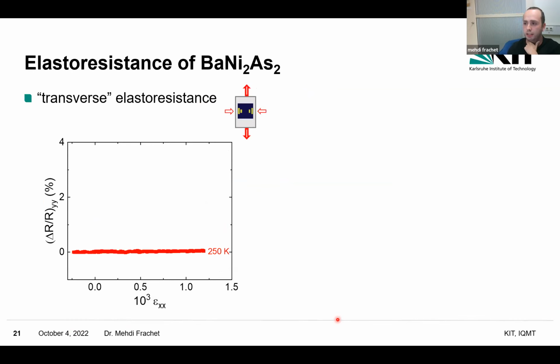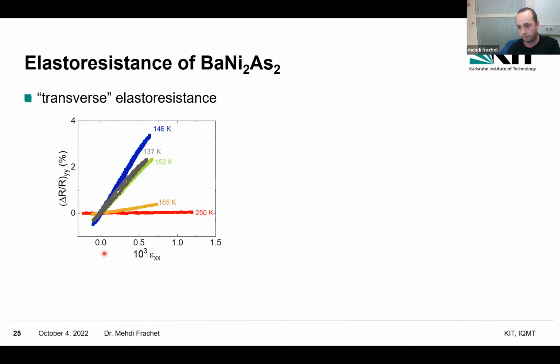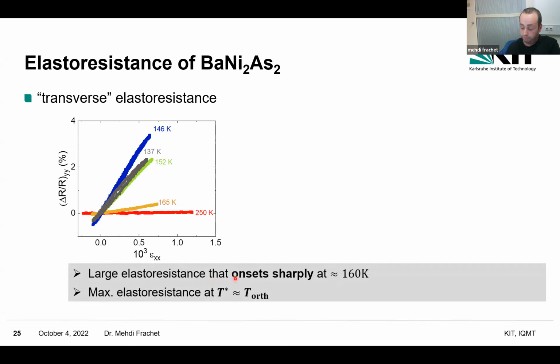Okay, now let's apply some voltage and have a look at the data that we got. That's transverse elastoresistance, so the electrical resistance is measured perpendicular to the pulling direction. Resistance as a function of strain, and you see that at high temperature there is not so much response to strain down to something like 165, 160 Kelvin. But below that temperature, there is a sharp and quite large response that develops. It's maximum close to 145, 146 Kelvin, and when we cool down further, it weakens again. So a large elastoresistance that onsets sharply close to 160 Kelvin, and a maximum of the elastoresistance at this T star temperature, which is very close to the orthorhombic transition temperature.